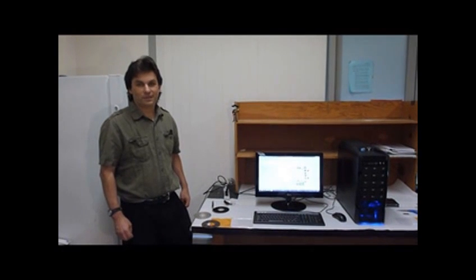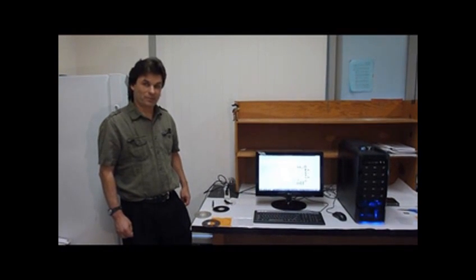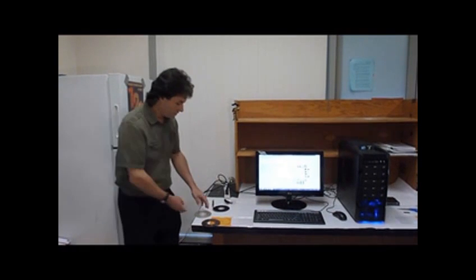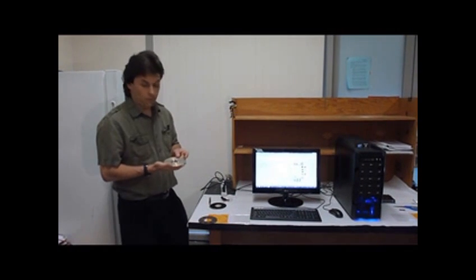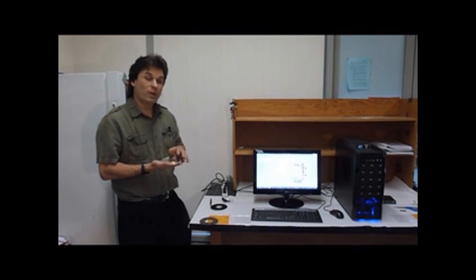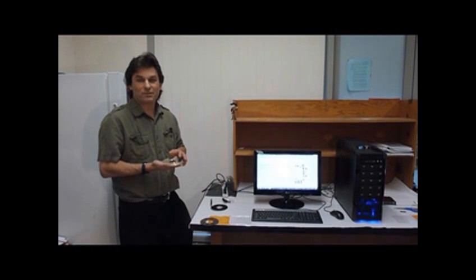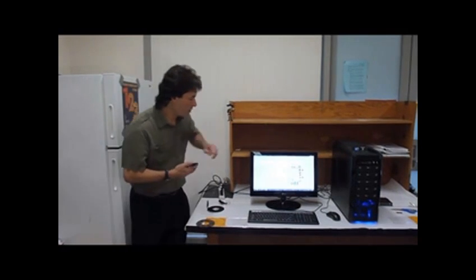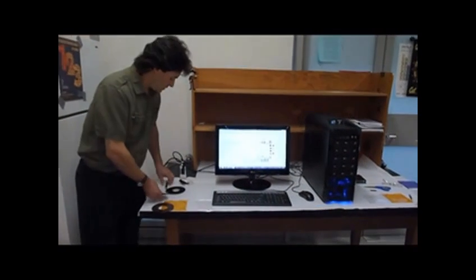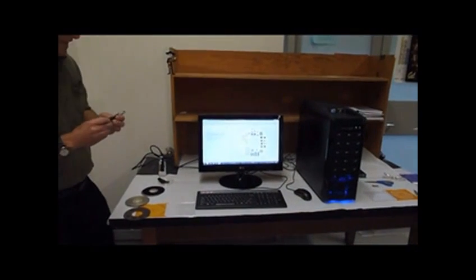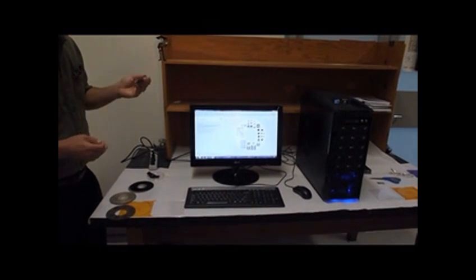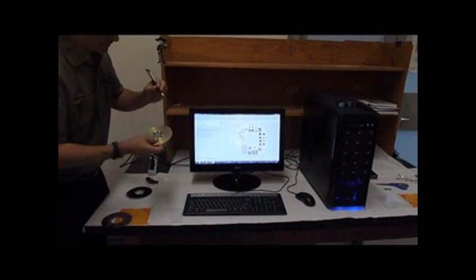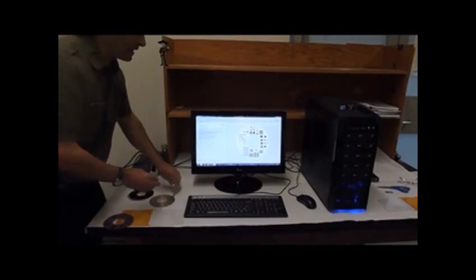And I'm here today to tell you about our work on carbon-based supercapacitors. We start with an ordinary compact disc. We put a sheet of plastic on it. We coat it with graphite oxide, an inexpensive precursor to carbon-based materials. We can then, on a computer, draw designs. We can put it in a disk drive, and using a laser scribe device, we hit it with an inexpensive infrared laser, and we can make a pattern.